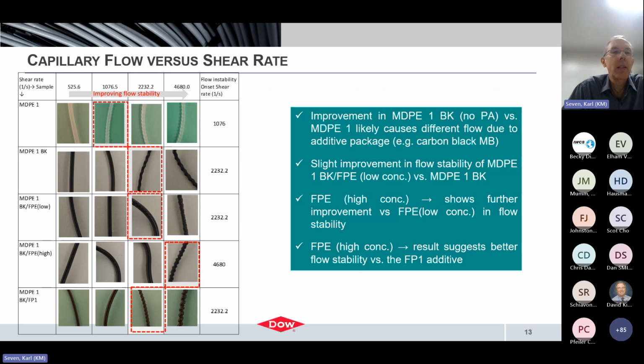That's likely due to the fact that the fully formulated jacket compound does have a slightly different additive package, which plays a role in how the compound flows through the capillary. Then as I move to the third series of pictures, MDPE1 BK FPE, that shows further improvement in flow stability. As you can see in the picture, you have to look a little closely there. There is flow instability at the same shear rate, but it is slightly improved versus the sample without the processing aid.